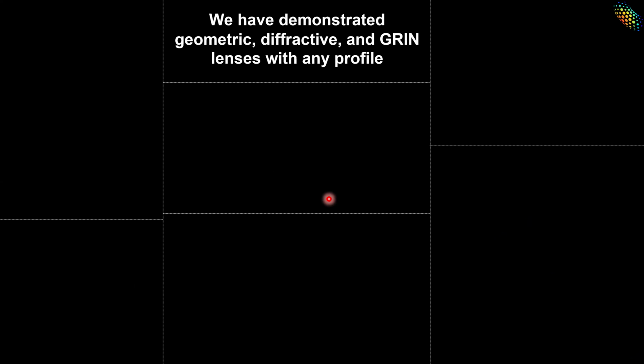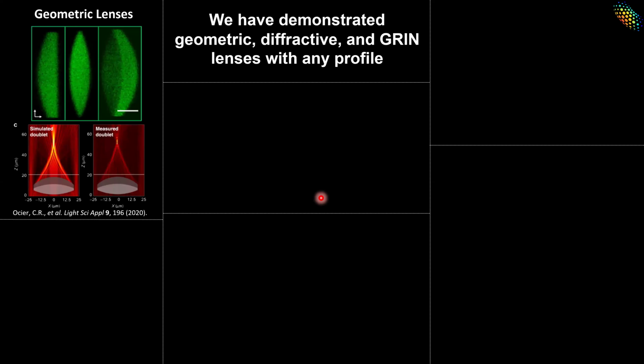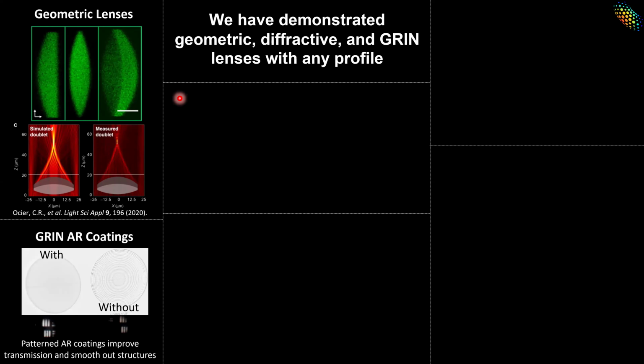So in terms of things that we've made, we're just going to go through a library of things. We've demonstrated a wide variety of geometric, diffractive, and GRIN lenses with any kind of profile. These range from standard geometric micro lenses. One interesting thing we can do is directly put gradient index anti-reflection coatings on these. This is just a matter of going from the high index of the lens itself to the low index of the background over a micron scale distance.